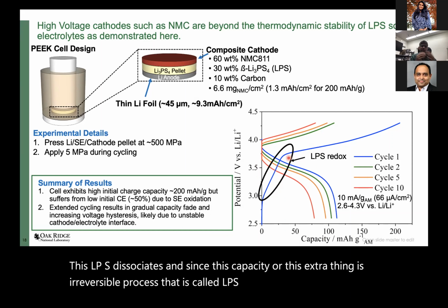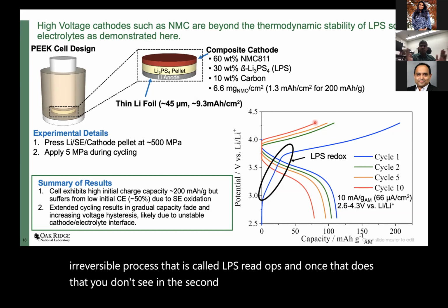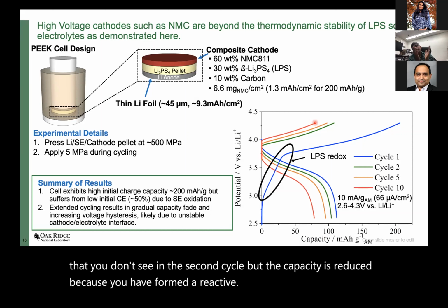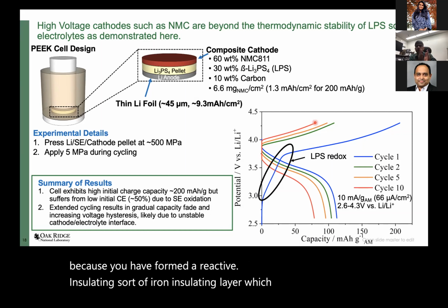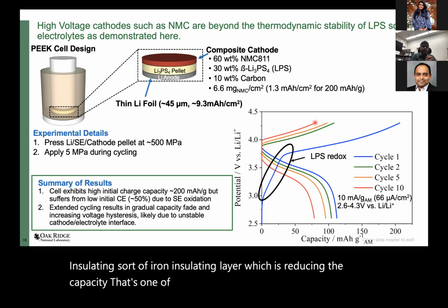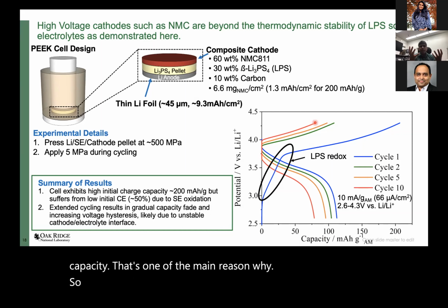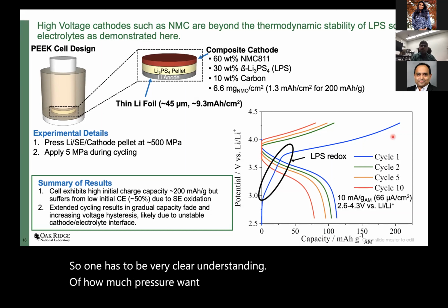Once that happens, you don't see it in the second cycle, but the capacity is reduced because you have formed a reactive, ion-insulating layer, which is reducing the capacity. That's one of the main reasons why. So one has to be very clear in understanding how much pressure to apply to get this kind of charge-discharge.